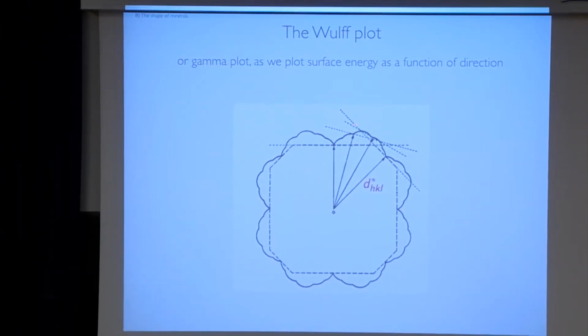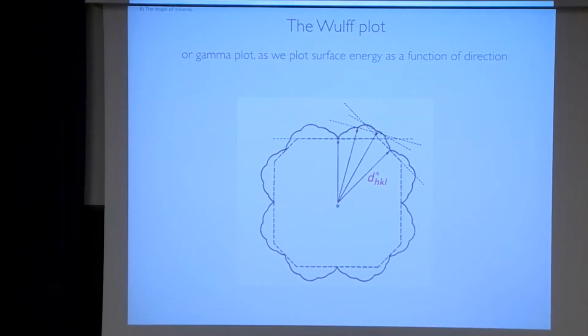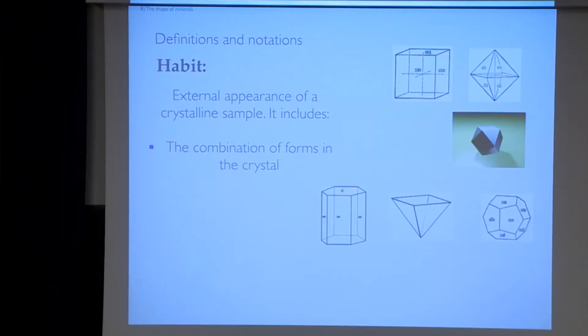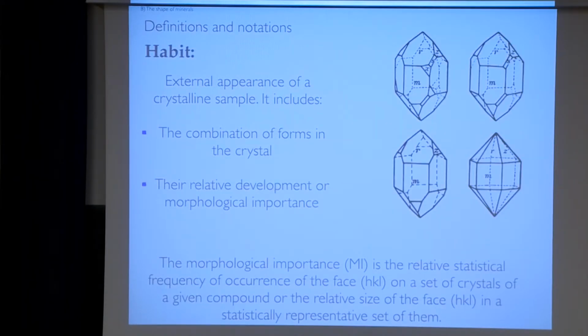Okay, but it is not possible to have continuous curvature for a single crystal, I mean a normal single crystal, no impurities, just a pure crystal growth problem, right? There is no way to have continuous curvature. So you always have faceted planes, okay? But you can have different kinds of habit. The habit will depend on the different growth rates, I mean, actually the ratio of the different growth rates in a growing crystal, and on the combination of forms of the crystal. So you can have different kinds of habit, but always the habit will be formed by flat faces.